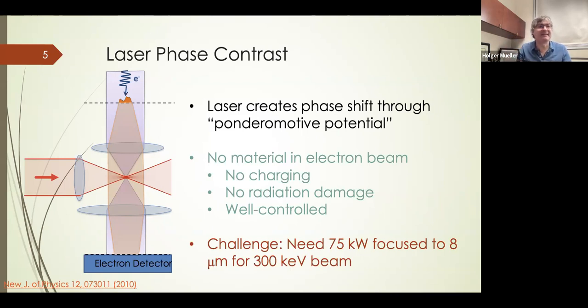And so now there is a net effect, even after averaging one oscillation. And that net effect can be described by the ponderomotive potential. And if you do the quantum mechanics, the ponderomotive potential can lead to the needed phase shift of the electron beam. If that worked, there would be three advantages, and they all arise from the fact that there's now no material whatsoever in the electron beam.